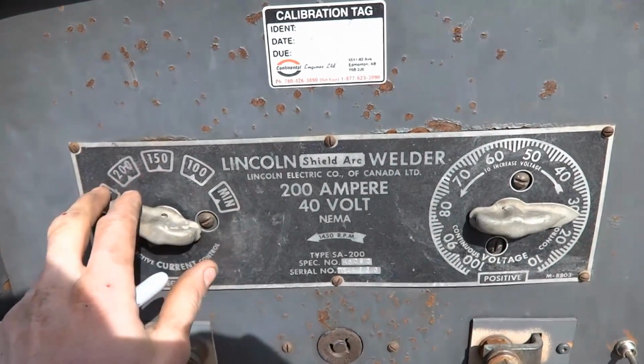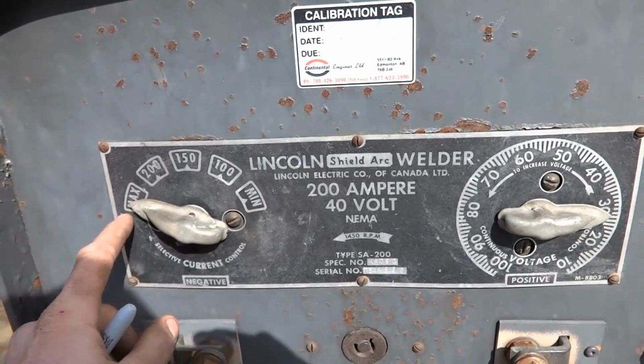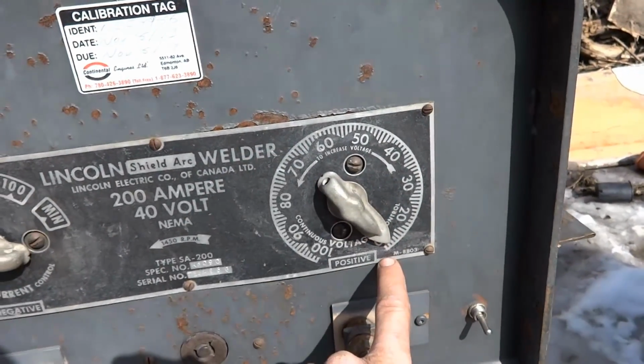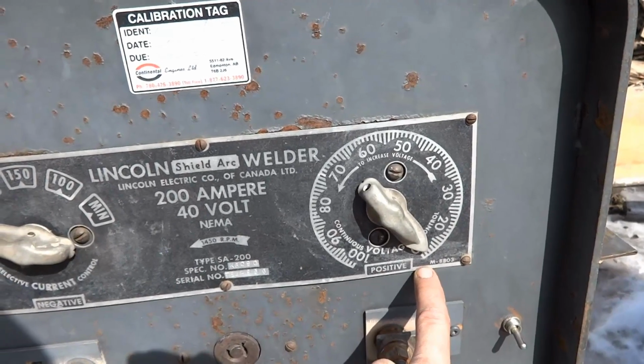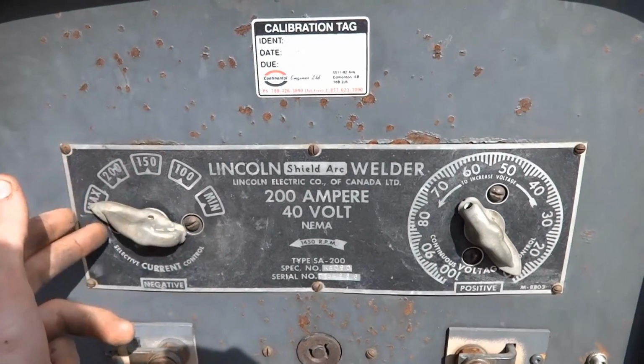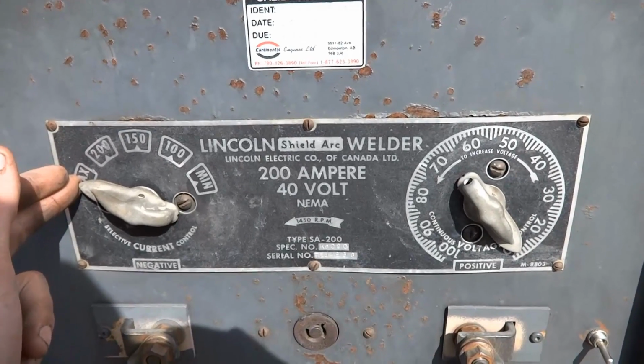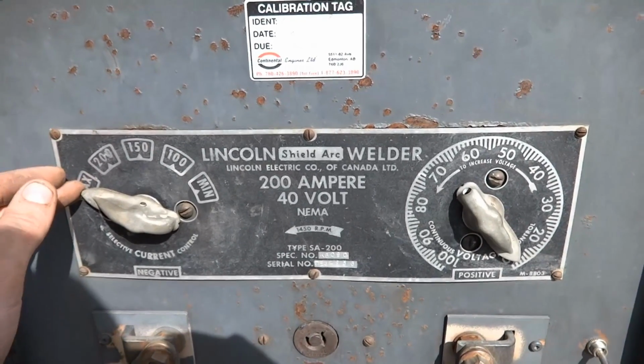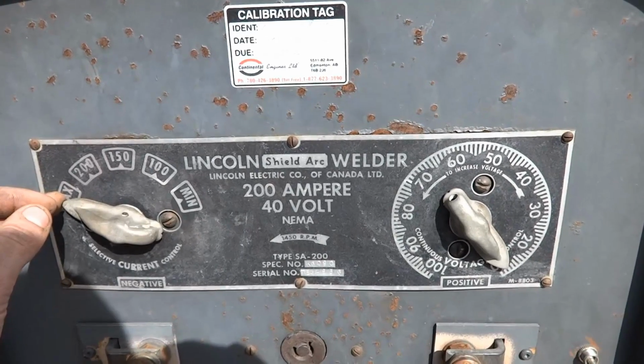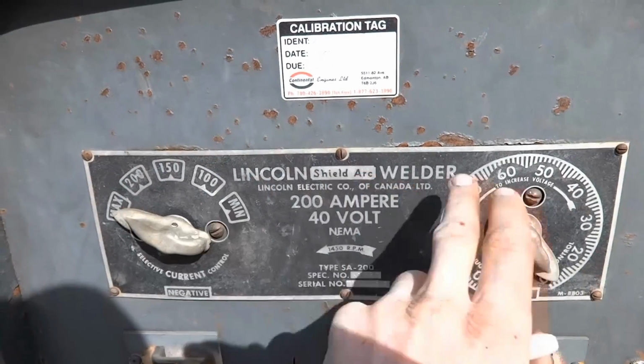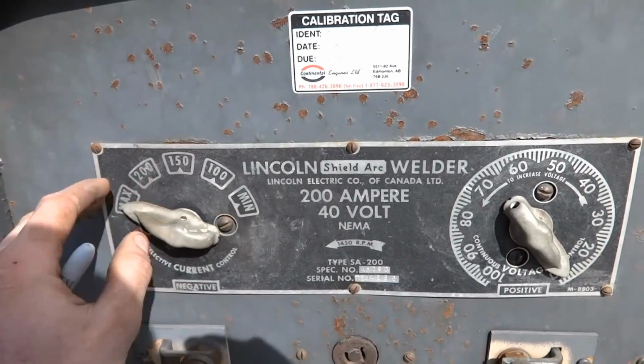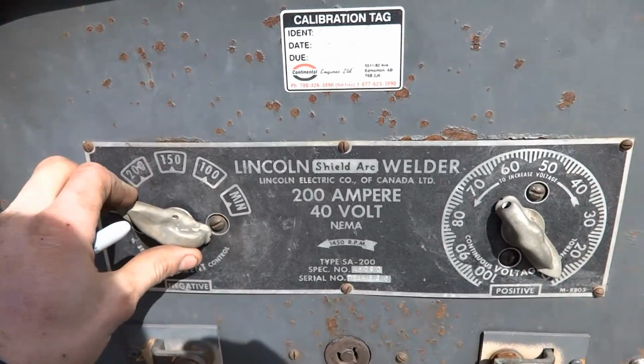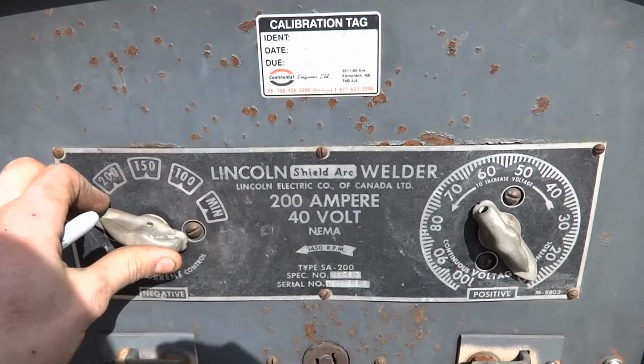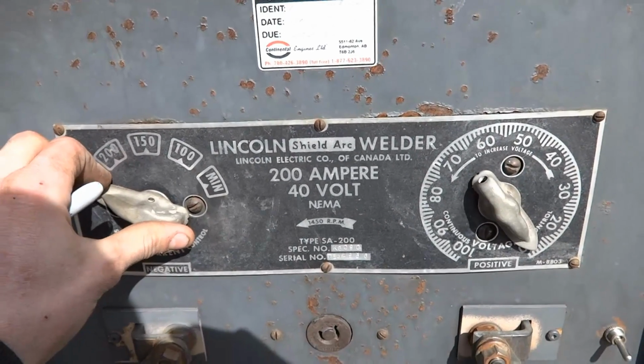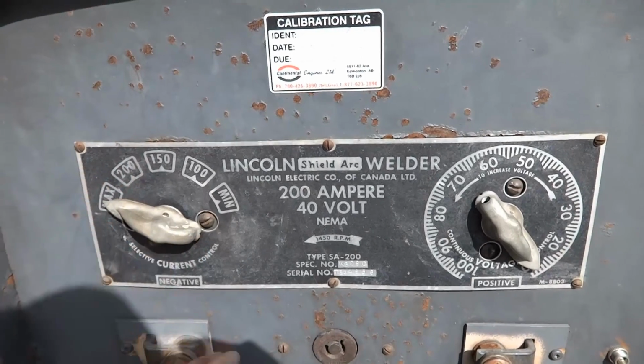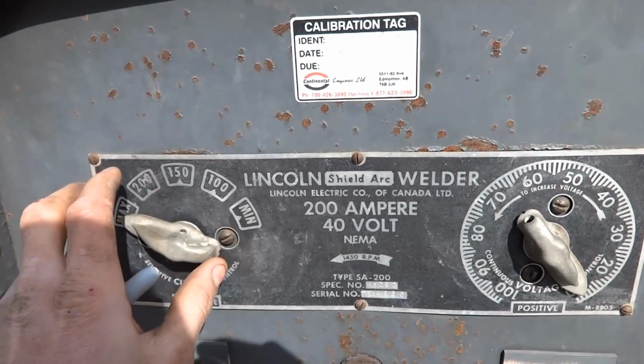The 1969 Lincoln Redface behind me, I can burn at fifth gear and drop the voltage all the way to 10, doing position weld. I'm able to deposit a lot of metal in a very short amount of time due to the volt amp curve, due to using arc length manipulation, due to the fact that I'm more amp heavy than volt heavy, so I'm able to hold a very tight arc and push on the electrode. I will not snuff out. Burn off rate increases because I'm holding a tight arc. As amperage increases, voltage drops off. So I'm able to deposit a lot of metal in a very short amount of time.